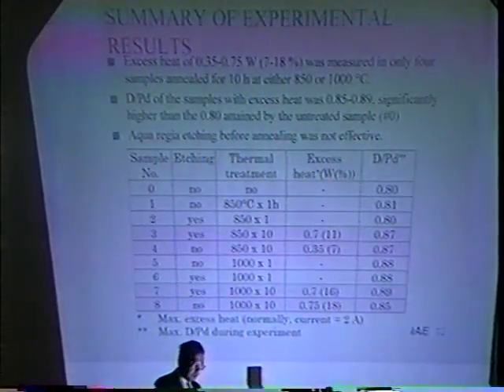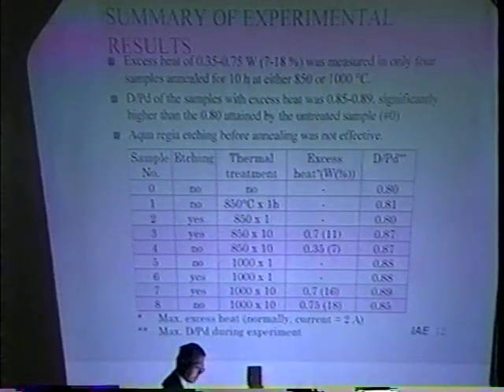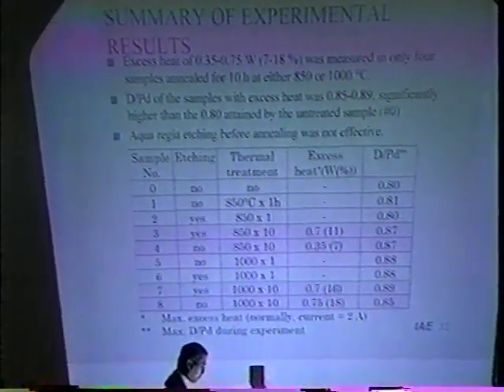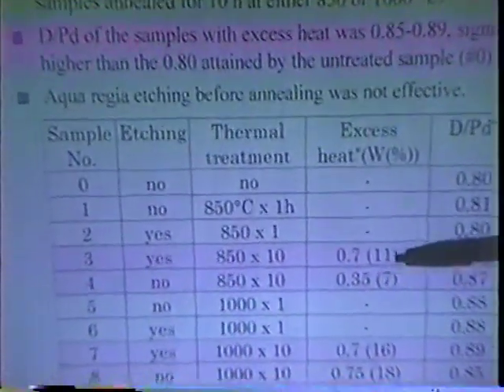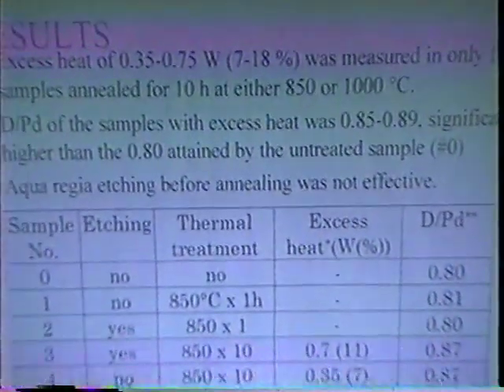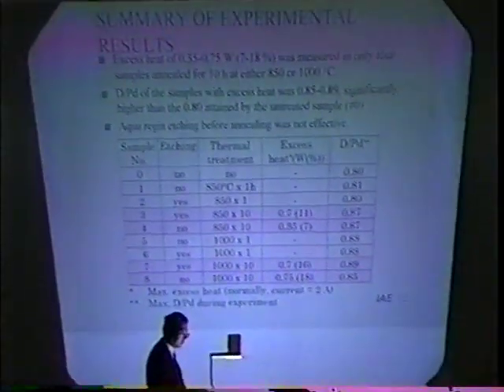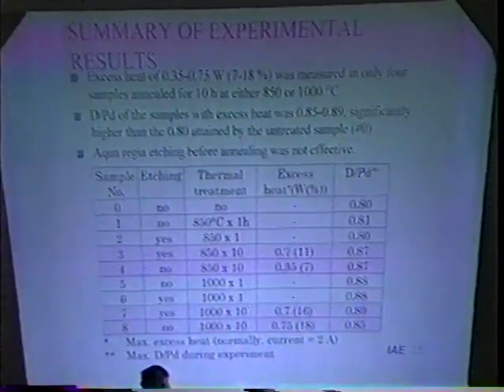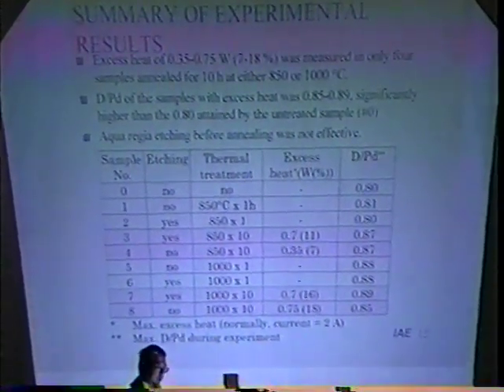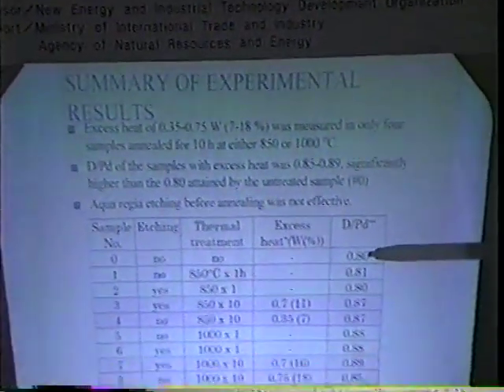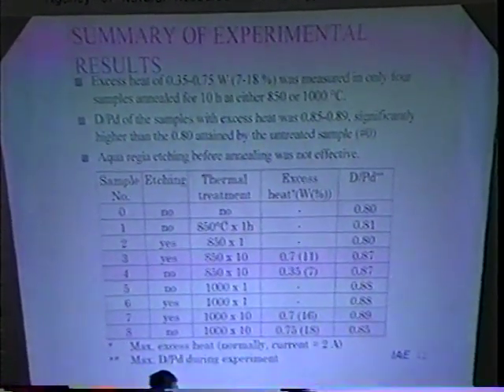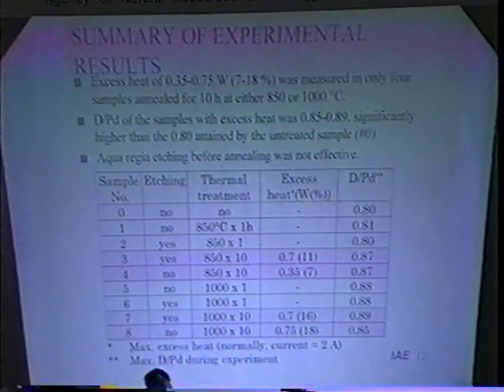This slide shows a summary of our experimental results. From the results, it seems that excess heat of 0.35 to 0.75 watt, 7 to 18% of electric input power, was measured in only 4 samples annealed for 10 hours at either 850 or 1000 centigrade. The D/Pd of the samples with excess heat was 0.85 to 0.89, significantly higher than 0.8 attained by the untreated sample. And aqua regia etching before annealing was not effective in our experiments.